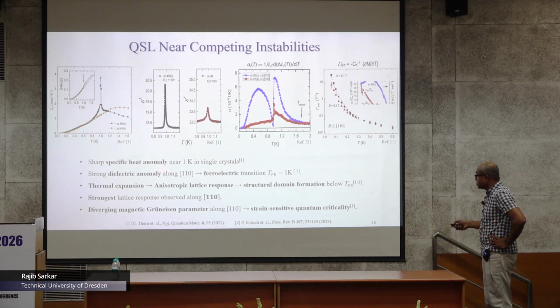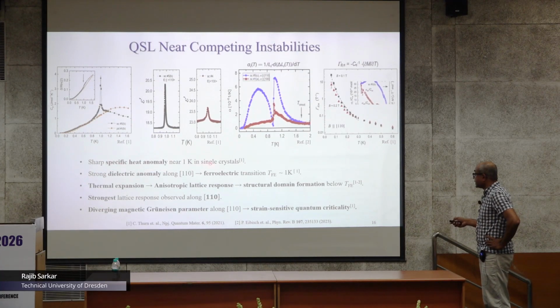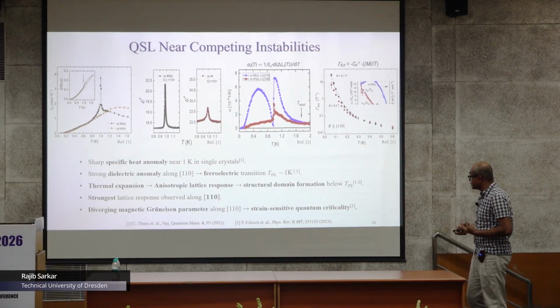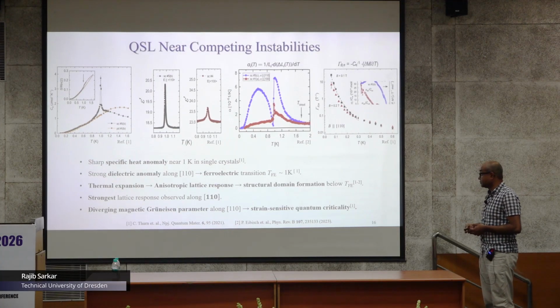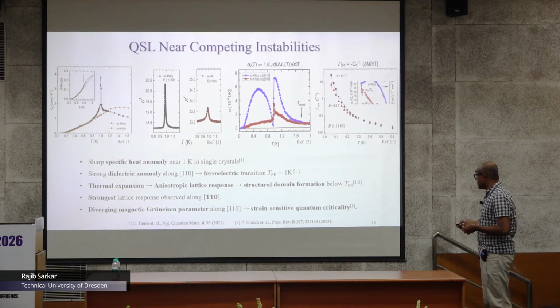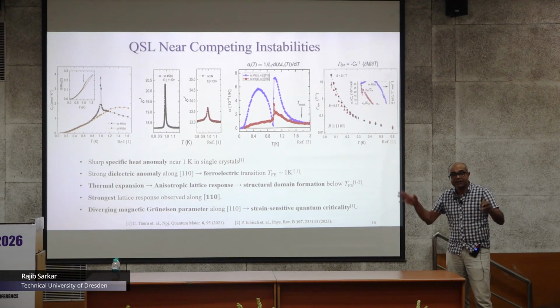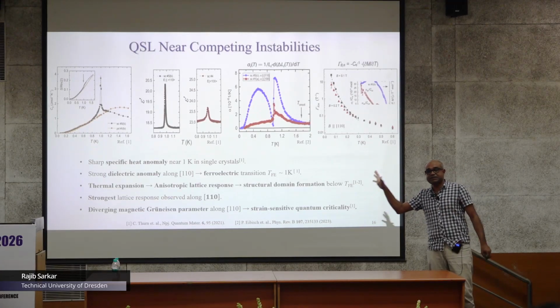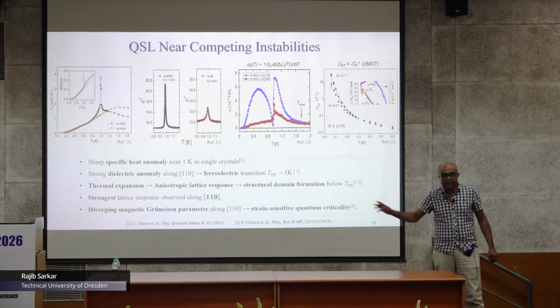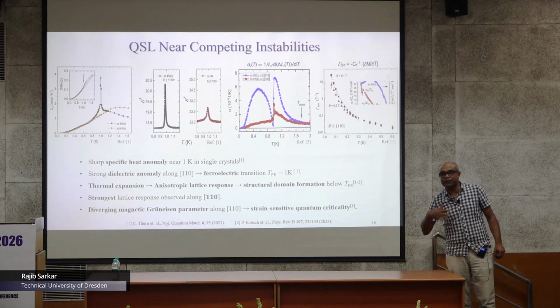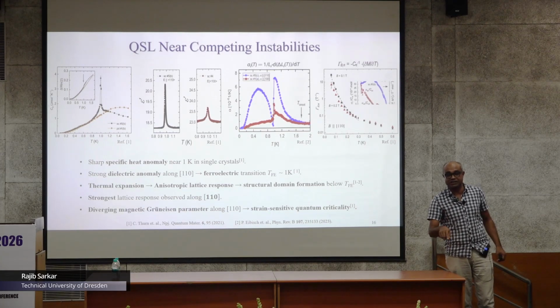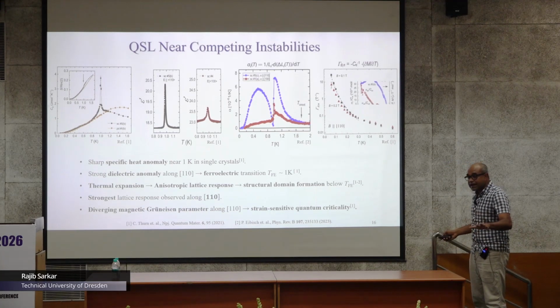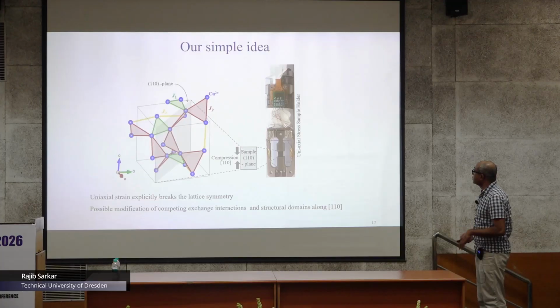It also has many other degrees of freedom. It has a specific heat anomaly at 1 K, which is related to a ferroelectric transition, it has a strong thermal coupling, and it also has a strain sensitive quantum criticality. So we have a lot of competing energy scales in this system. Therefore it was a very suitable candidate for us to tune and play around with, and we did it. It took some time, but it worked. Only last year did we finally get some results.